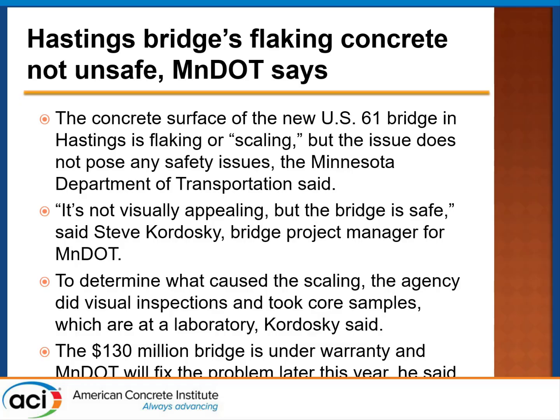We ended up removing all of the concrete under warranty work. I think it's a defect in the design. And replacing it with a cementitious material that is still there. In fact, they commented that some of it was flaking off, and it is flaking off where the 18-wheeler ran into it and appears to have ridden up on the balustrade wall for a little while. It's flaking off there. Other than that, it's in great shape.